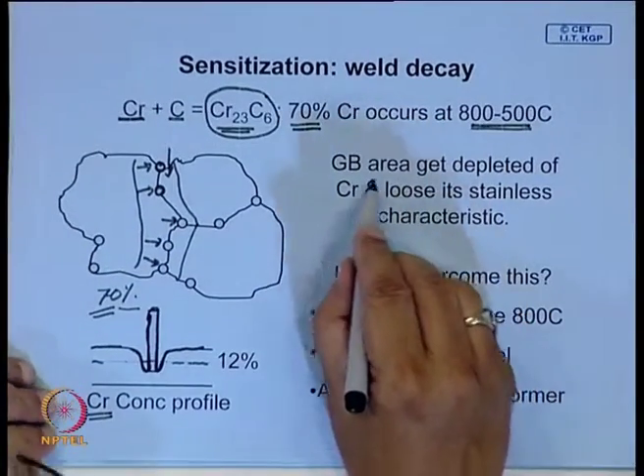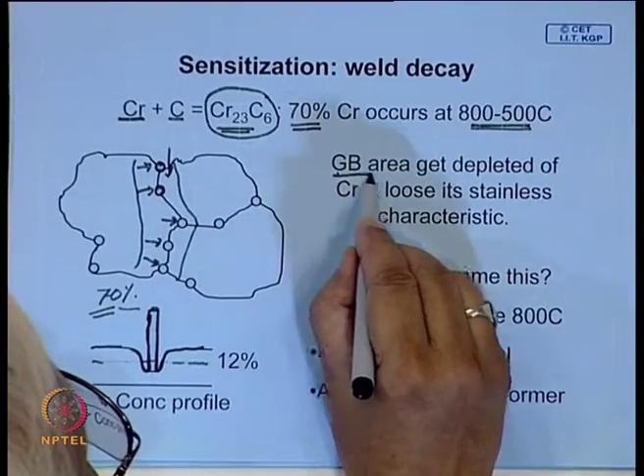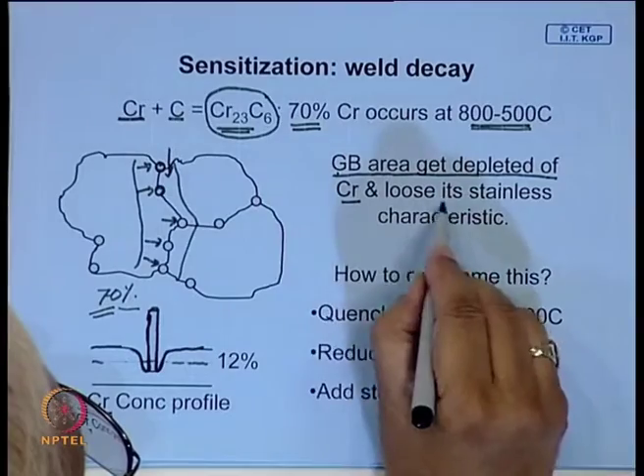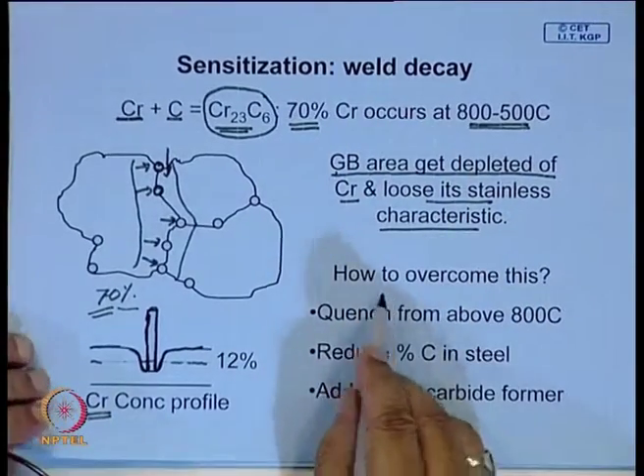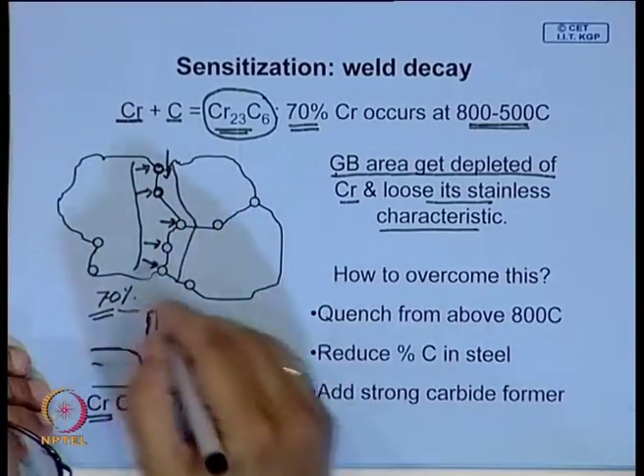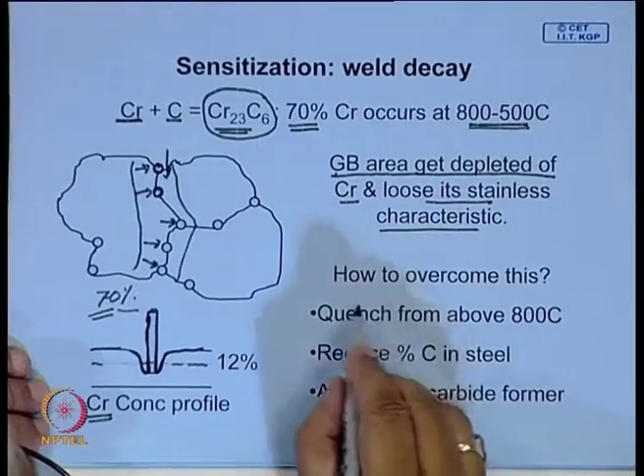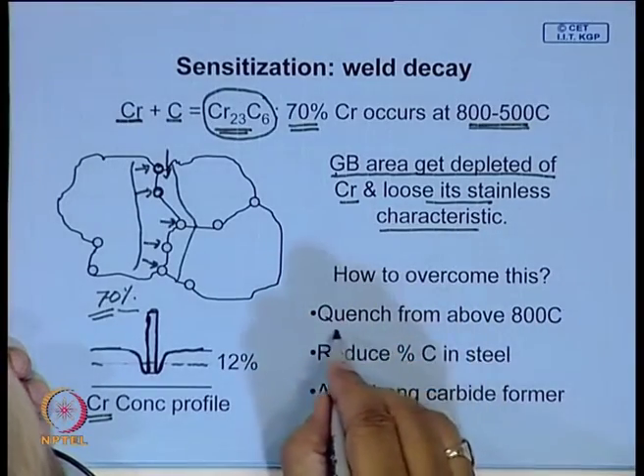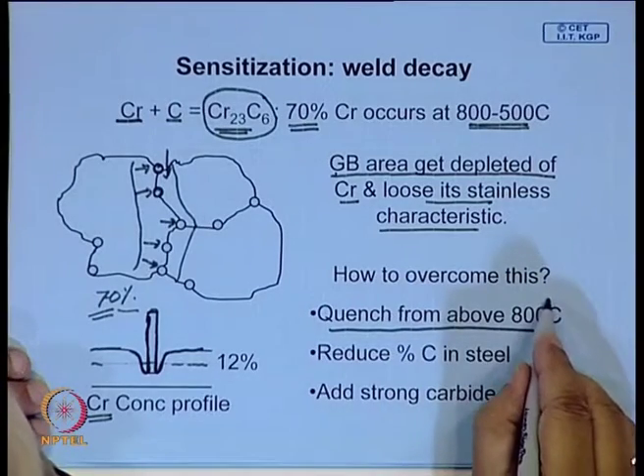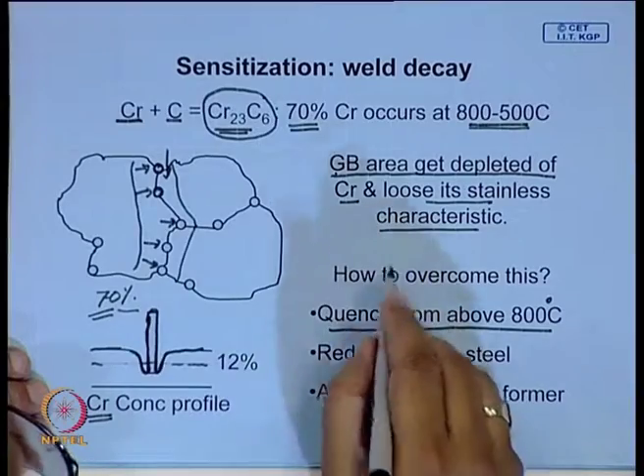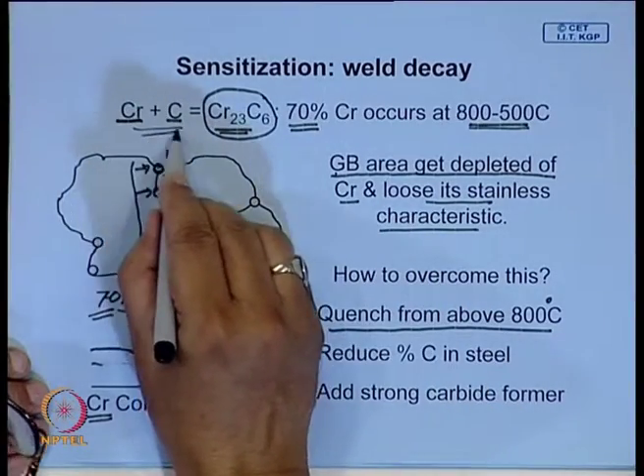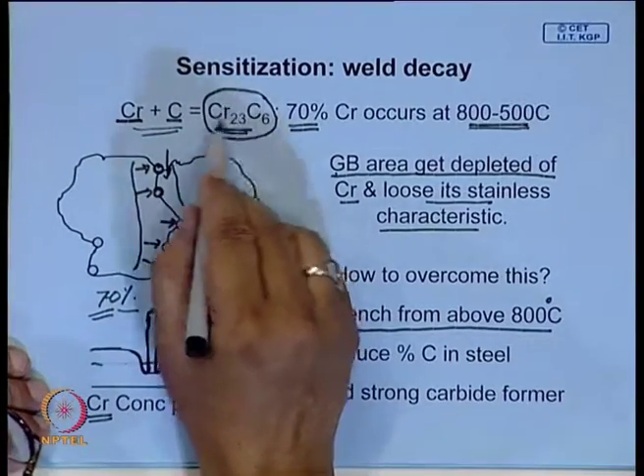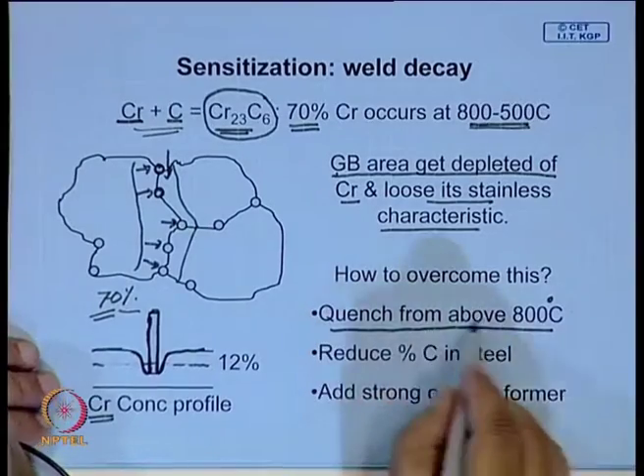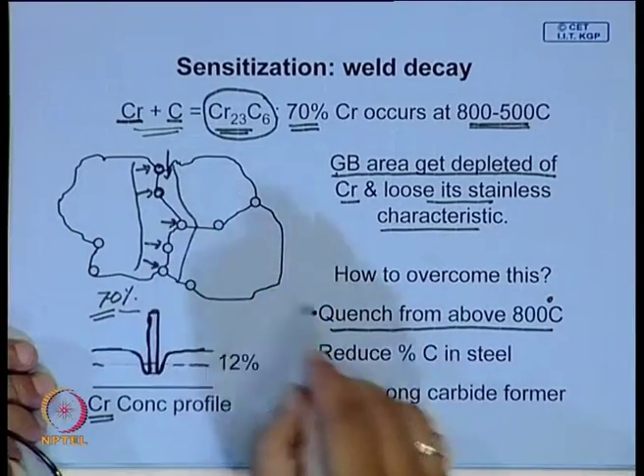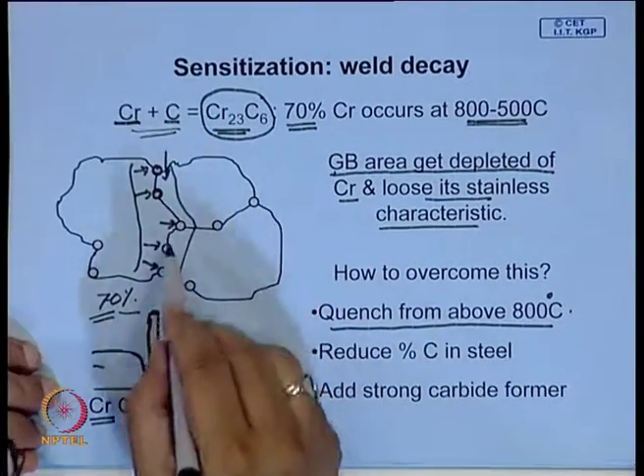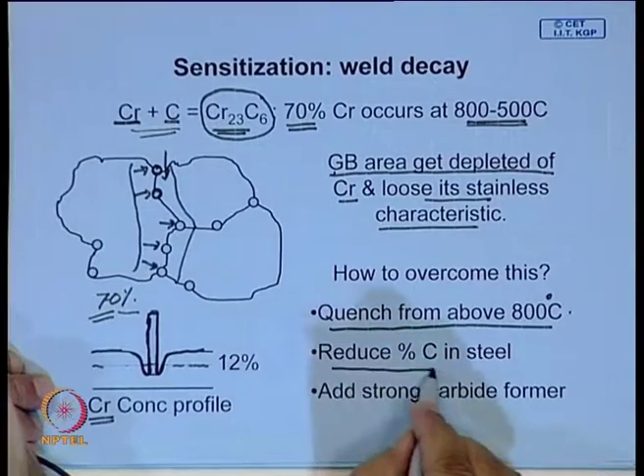The main reason for this is that the grain boundary area gets depleted of chromium and loses its stainless characteristics. Therefore, grain boundaries are susceptible to attack, and hence it is susceptible to intergranular cracking. And how to overcome this? One way is to quench from above 800 degrees centigrade, which is not always possible; then you do not get enough time for this reaction to take place, because above that most of this is soluble in the matrix. But if a material has been sensitized, this treatment can overcome that problem. The other alternative is to reduce carbon.